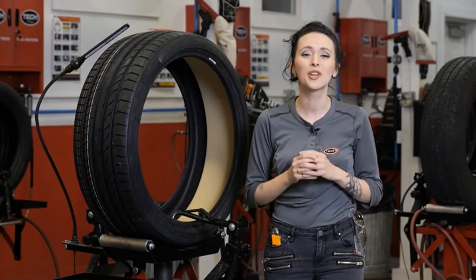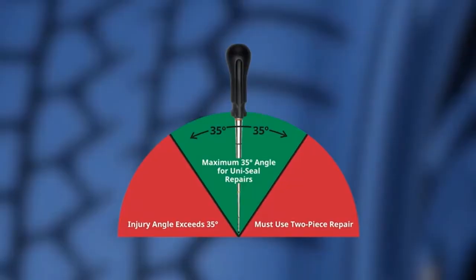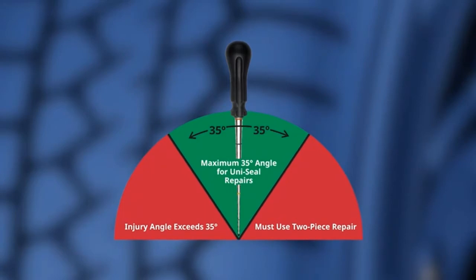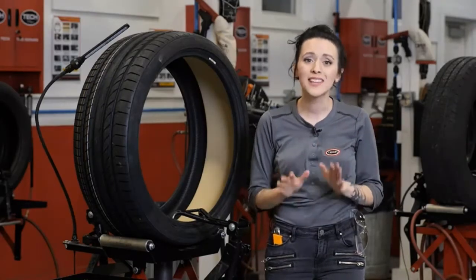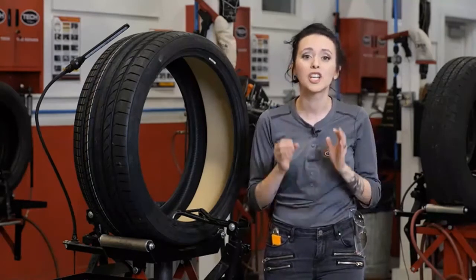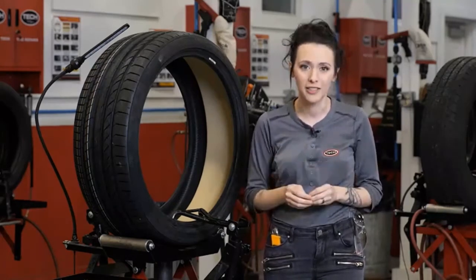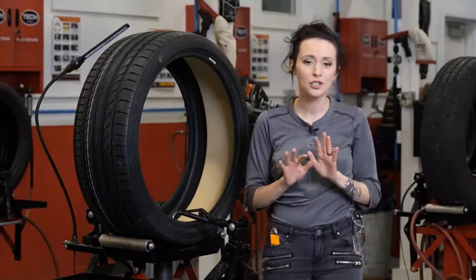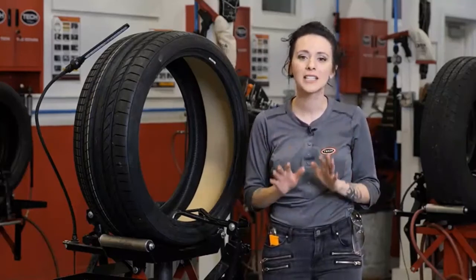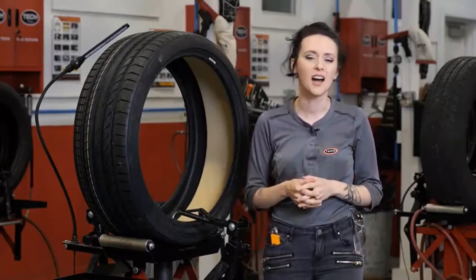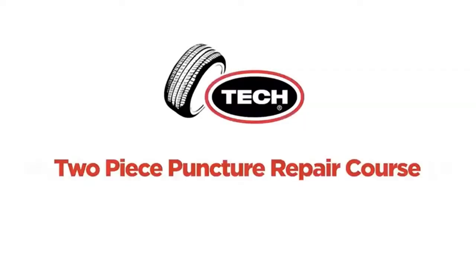Once it's determined which type of adhesive is present, use Tech's TRT 105 inspection tool to quickly and precisely measure the size and the angle of the injury. The injury size and angle are 2 critical pieces you will need to select and install the appropriate repair. Please note, if the injury angle exceeds 35 degrees, a 2-piece repair must be used.